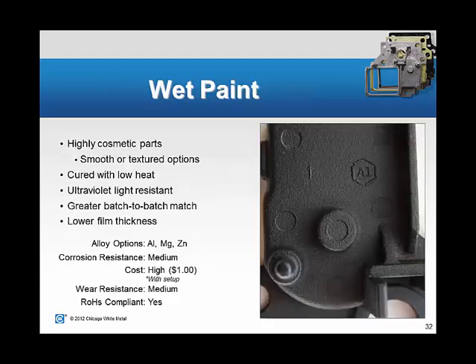If we look at the wet paint, again, what we would consider a finish for highly cosmetic parts, it comes in a smooth or textured option. As you can see in the picture, that's a textured look with a wet paint. I know it almost looks like a powder-coated part, but it is a textured wet paint. It cures with lower amounts of heat, so outgassing with wet paint is not nearly as much of a concern. It has UV light resistance capability, and greater batch-to-batch matching and lower film thickness than the powder coating.